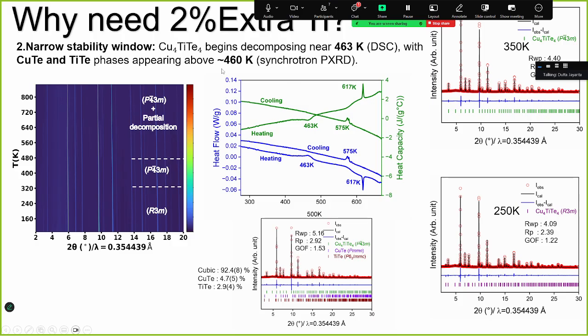Another reason is that its stability is very narrow. From DSC, the cubic phase decomposes at around 463 Kelvin, and from synchrotron also it shows it's partially decomposed into copper telluride and titanium telluride above 460 K. So it's quite challenging to stabilize that phase. If you do slow heating or slow cooling above 460 K, then the phase decomposes.